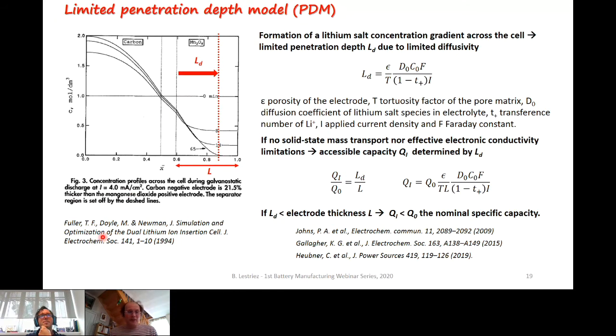Building on the work by Fuller, Doyle, and Newman, Johns and Gallagher have established a simple equation to determine this limited penetration depth as a function of the electrode porosity, its tortuosity factor, the diffusivity of the electrolyte, its salt concentration, the transference number for the lithium cation, and also the applied current density. If you have no solid state mass transport limitation and no electronic conductivity limitation, then you can estimate, as an approximate model, the accessible capacity by simply comparing this limited penetration depth to the electrode thickness, and also taking into account the specific nominal capacity.